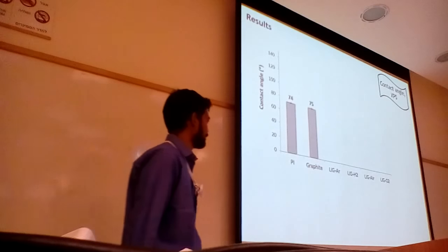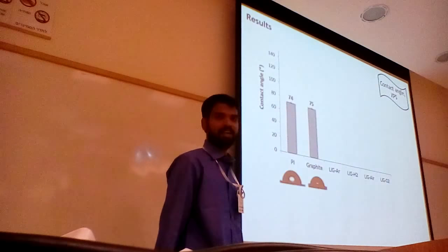The contact angle for our control samples is hydrophilic, and these images display the degree at which a water droplet interacts with the surface. If the contact angle is less than 90, it is hydrophilic. If it is more than 90, it's hydrophobic. If it is around 90, they are partially wettable. Now, the graphene fabricated under inert atmosphere like argon and then in the hydrogen box is super hydrophobic.